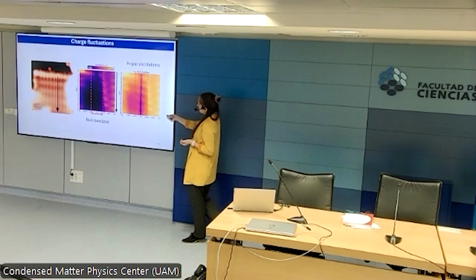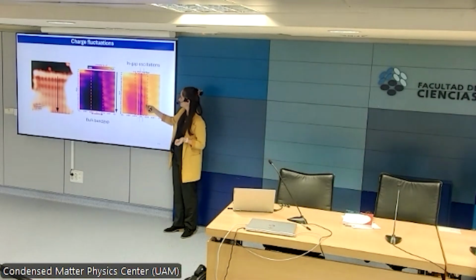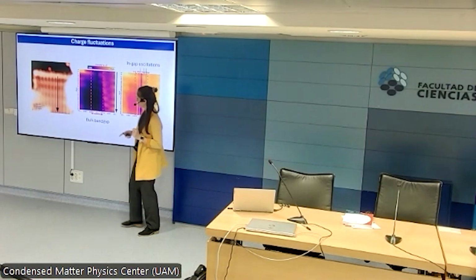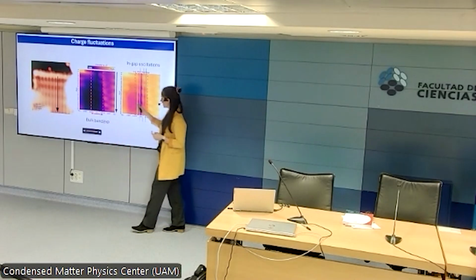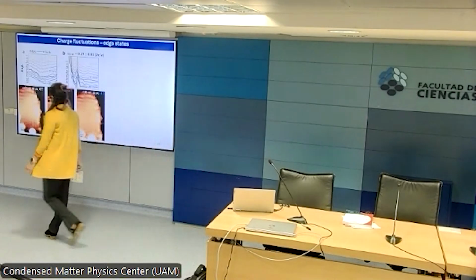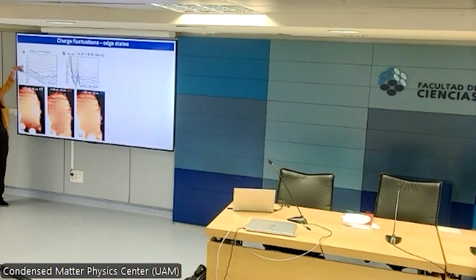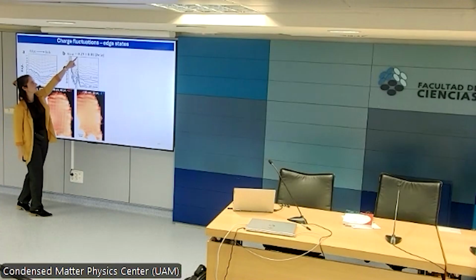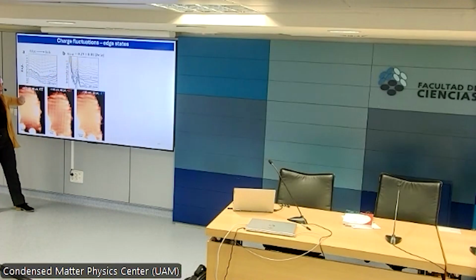To better analyze these in-gap oscillations, we take vertical line cuts in this band gap. So the process is the dI/dV map, log scale, take vertical cuts. And I'm plotting the cuts here. Every line is a cut inside the band gap, and you can see that there are very clear modulations of the density of states. Note that this is in a log scale, which means that the oscillations are decaying with the same speed as the topological edge, which means that they're imprinted on the topological edge. The interesting bit is if we look at the top, these oscillations have a very, very fixed frequency, which is about 0.29 2π/a, where a is one of the lattice constants. So all these oscillations are at the same frequency.